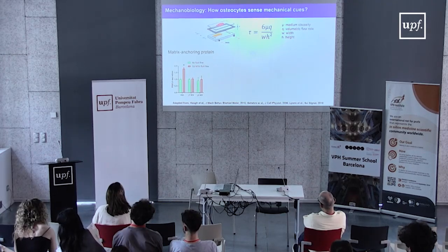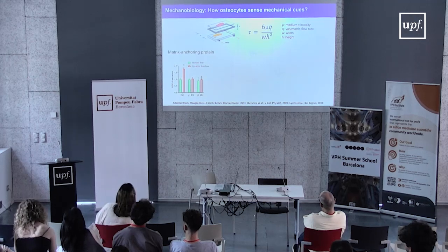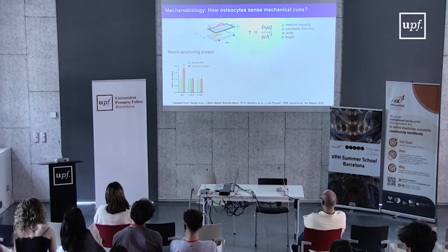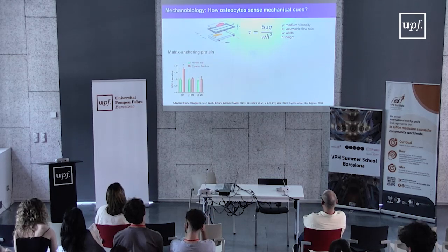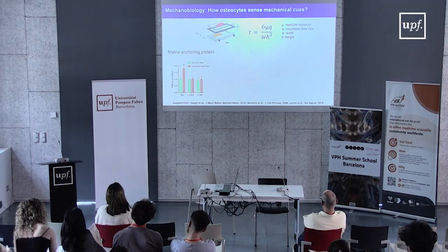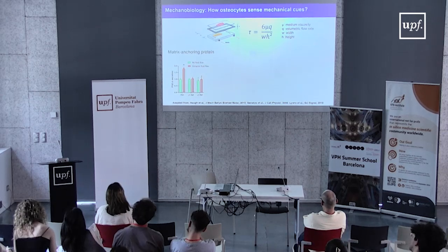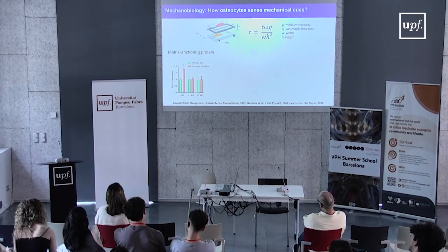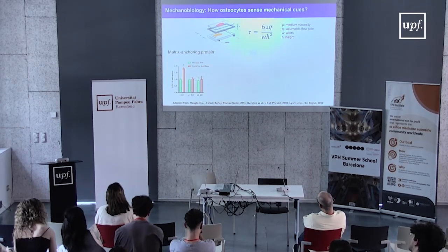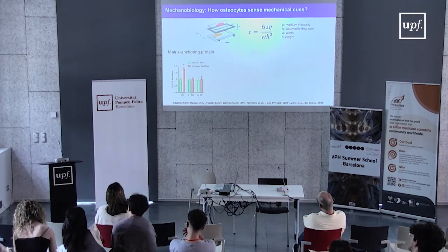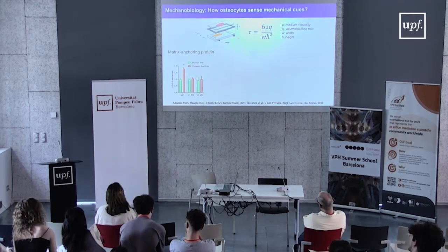Just to emphasize the role that matrix anchoring proteins can have on the osteocyte network, if we do this type of experiment and we induce, by siRNA knockout, the loss of specific integrins, which are the proteins that will anchor the osteocyte membrane to the extracellular matrix, if we knock out the beta-1 or beta-3 integrins, you see that osteocytes are no longer capable of responding to dynamic fluid flow.